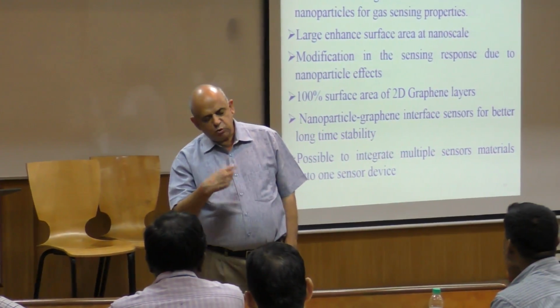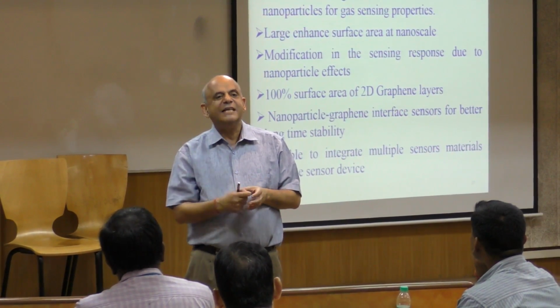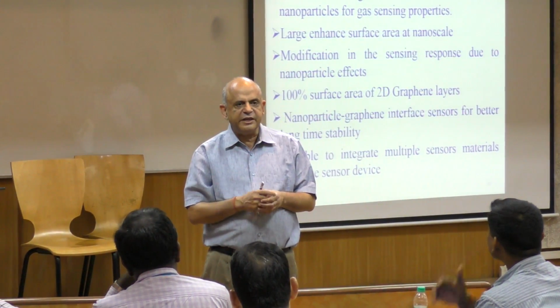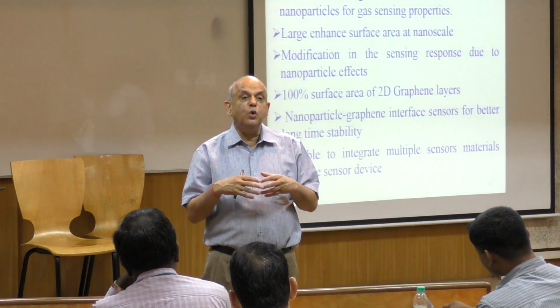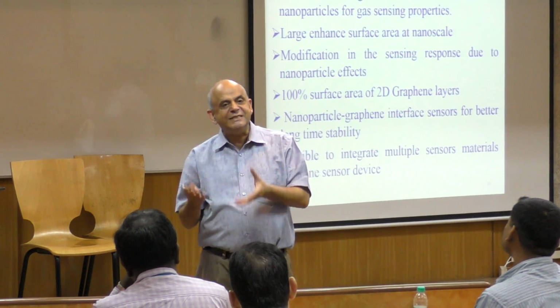Yes, so this is the method to do it, because you can't work with one sensor. This is a problem with oxide sensors, exactly what you are talking about. For example, tin oxide responds similarly to most reducing gases, and its response to oxidizing gases is similar. It cannot differentiate, but its sensitivity is different.